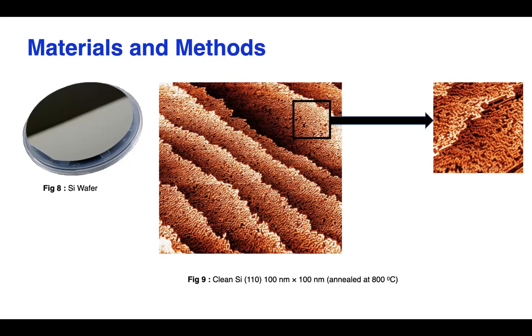This silicon wafer comes with an oxide layer on top of it, so we have to remove the oxide layer. How can we remove the oxide layer? We have to flash anneal the sample. Normally during the flash annealing, we heat the sample to almost 1200 degrees Celsius. Otherwise, we will not be able to remove this oxide layer from the sample. Once we remove the oxide layer, we can see the silicon atoms.